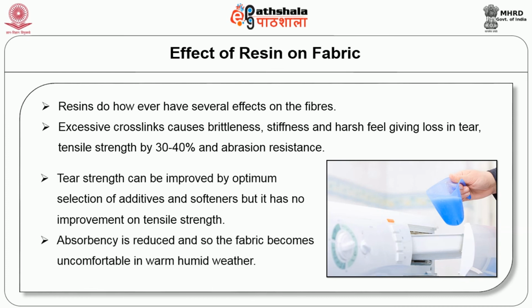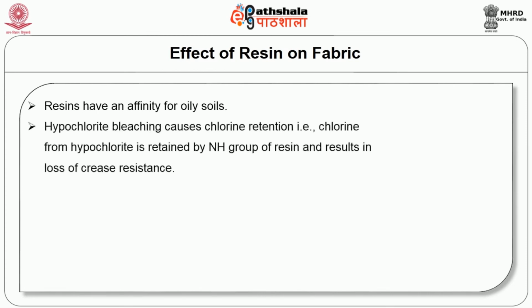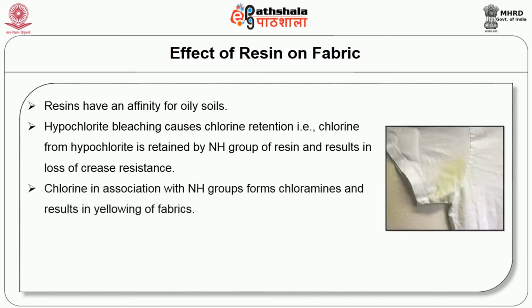Absorbency is reduced and so the fabric becomes uncomfortable in warm, humid weather. Resins have an affinity for oily soils. Hypochlorite bleaching causes chlorine retention, that is, chlorine from hypochlorite is retained by the amine group of the resin and results in loss of crease resistance. Chlorine in association with the amine groups forms chloramines and results in yellowing of fabrics.